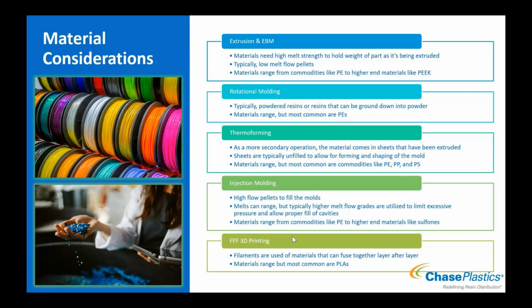And so you typically end up with a material with high molecular weight. You've got a lot of chain entanglement, and so it holds itself really well. That also correlates typically with a really low melt flow, because lower melt flows correspond to a higher molecular weight and higher melt strength. Materials range anywhere from polyethylene, so a standard 2 melt polyethylene that could be extruded, all the way up to PEEK. Maybe we're making rod stock out of PEEK, and then it can be machined into different components. So a huge option and variable range of materials for extrusion.